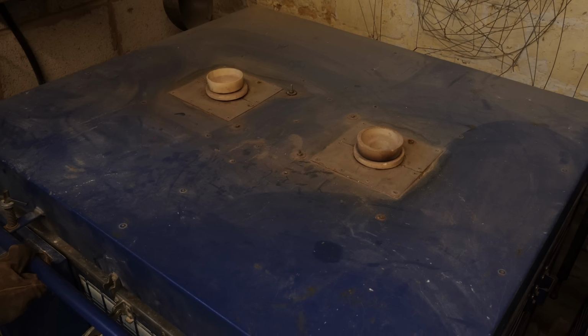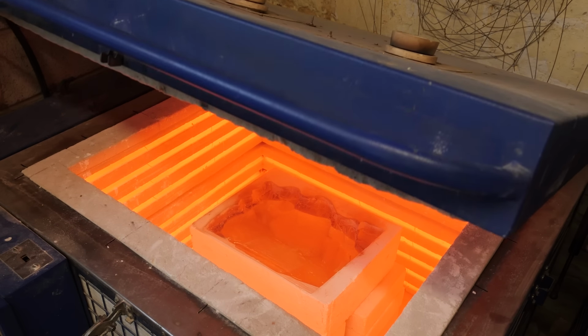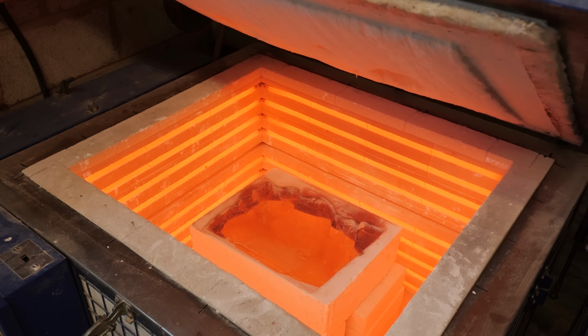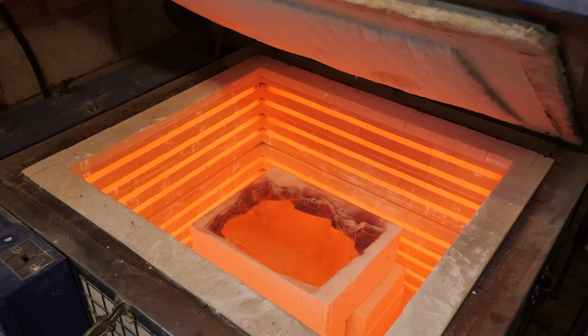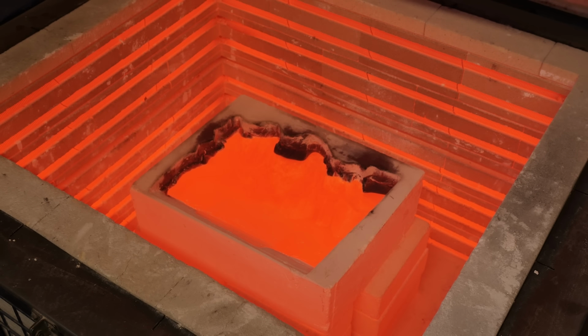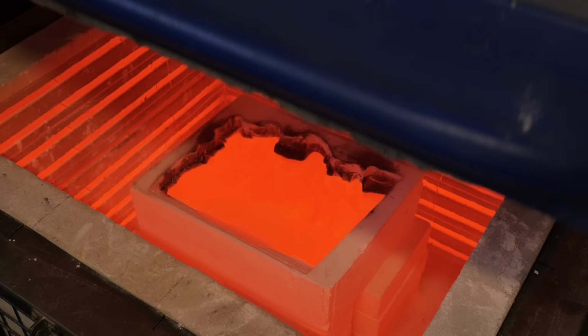The actual casting is fairly quick. It only takes a couple of hours for the glass to completely fill the mould and take the impression of all of the texture and the form. But then it takes 2-3 weeks, depending on the size of the piece, to cool it back down to room temperature. That's a controlled cooling, and it's in order to relieve any stress in the glass.